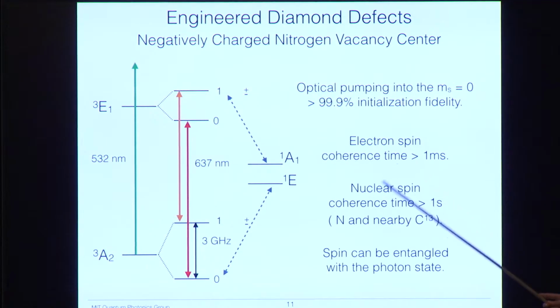The second is that this electron spin has coherence times that are longer than a millisecond. We can do 100 microseconds, a couple hundred microseconds, pretty easily in the lab without trying very hard. And we can also couple this electron spin to a nearby nuclear spin, which can have coherence times much longer, up to a second, maybe even longer if we try even harder. And then finally, we can entangle this spin state with the state of the photon.